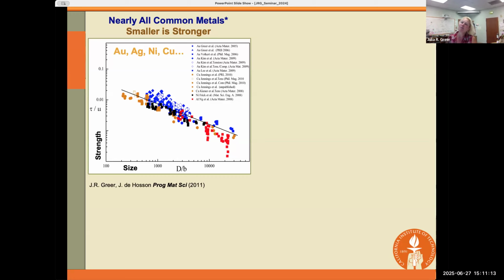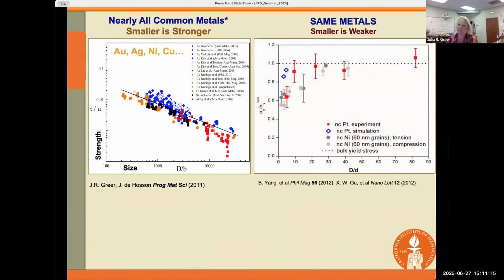Now, the size effect is more nuanced than that. If you look at the same metals like nickel, like platinum, etc., and now you deposit them using a different technique, for example, CVD or PVD or any kind of sputtering in its thin film form, now they contain grain boundaries. And all of a sudden, this effect is reversed. And now what you can see is that smaller is weaker. It's a more modest size effect. It's not plotted on a log-log plot, but it's non-negligible.